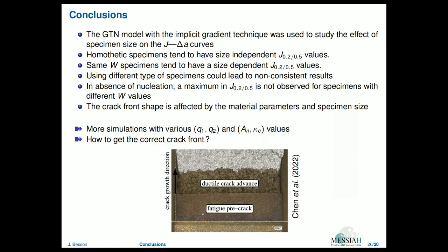The conclusion is also that toughness does not only depend on the thickness of the specimen, but also on its overall shape, which makes interpretation of tests even more complex. The problem is also how to get the correct crack front. Okay, so